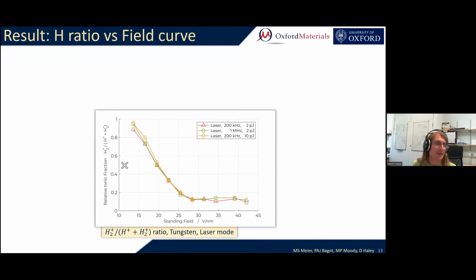What you see here is the relative ionic fraction of hydrogen 2+ to the sum of both hydrogen peaks. So essentially, that's a peak height ratio on the y-axis as plotted against the standing electric field in 3 laser mode experiments. The 3 experiments, you see it in the legend: 200 kilohertz, 2 picojoule laser mode. Second one is 1 megahertz, so 5 times as many pulses per time. And the last one is 10 picojoule, so 5 times as much energy per pulse.